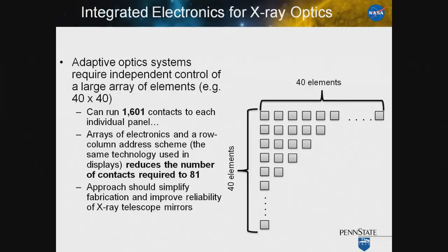So in principle, this technology shows that you should be able to make a next generation X-ray imager that has about a half arc second resolution. But there are some real challenges associated with this, the first of which is that each of the piezoelectric cells needs to be electrically addressed. So if we were to imagine a 40 by 40 array of piezoelectric cells, that means we need 1,601 contacts, one for the top surface of each one, and a continuous bottom electrode. And that becomes onerous, having to do the wiring off the device.